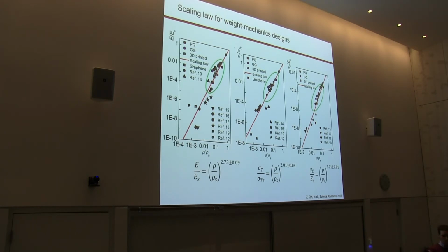Not exactly. I simulate the graphene assembly in a molecular dynamics model, because we don't have the facility to compress and heat up the graphene flakes. I simulate the process, how it might respond to the heat and pressure, and I form this structure. But the structure is not clearly defined because there's a lot of randomness for the particles I put inside my system, and their locations are not well defined at the beginning. That's why it ends up with a very random structure.